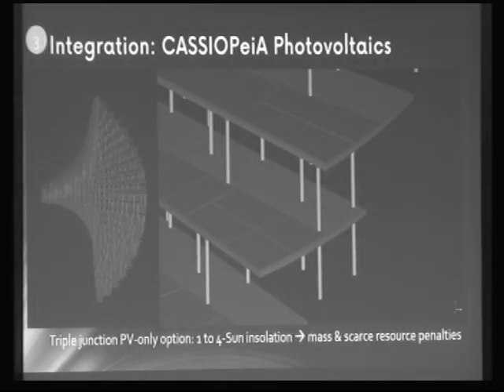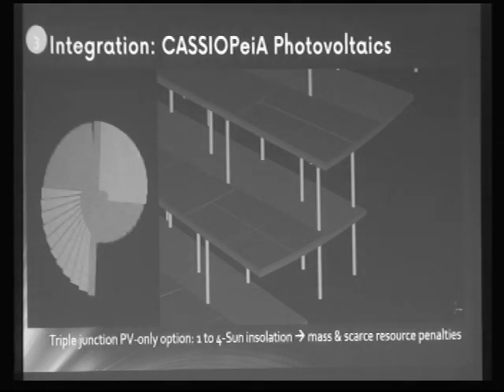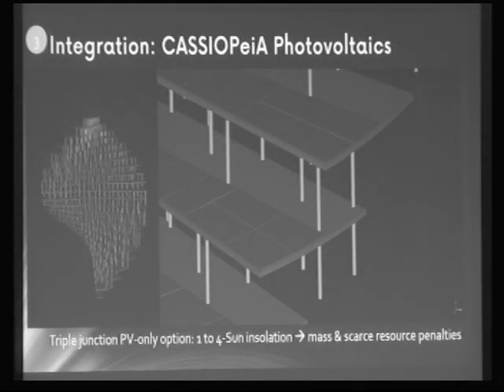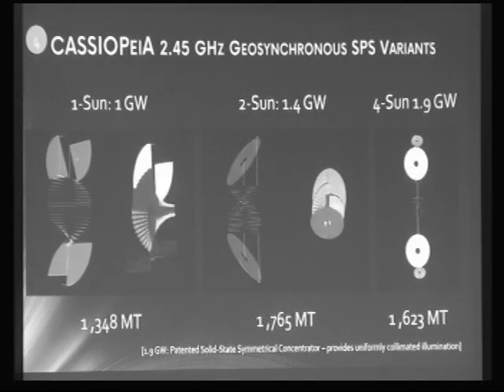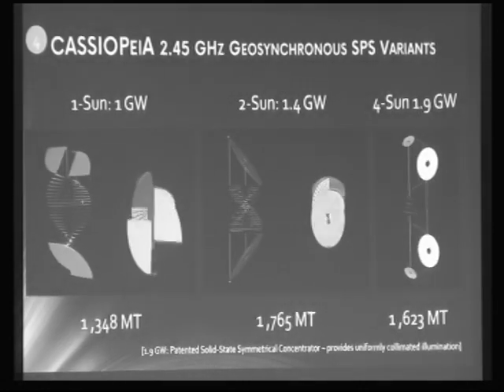Another example explored using standard PV rather than concentrated CPV. With 100-micron radiation-protection cover glass, this added a significant weight penalty — going from about 50% of the SPS mass to over 75% of the SPS mass in PV alone. Importantly, all the PV is being used; there is no redundant PV in this solid-state satellite example. Three satellite concepts range from one gigawatt to 1.4 to 1.9 gigawatts, using 45-degree quadrant reflectors.